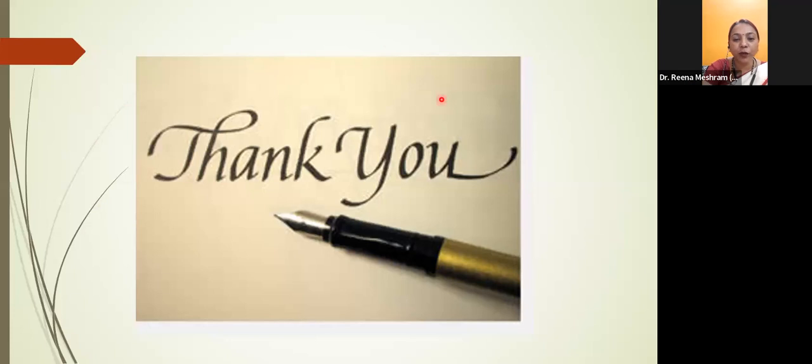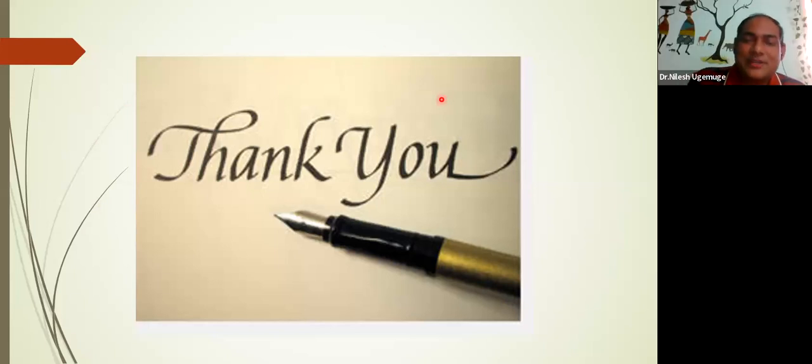Sir, Manjit Singh wants to ask, what is sinter and pre-sinter? Sinter means simply, what we do basically for getting phase purity, whenever we are trying to put material in a furnace. Before that, we heat that material at a very low temperature. Suppose you want to prepare your material at 600 degrees Celsius. Pre-sintering means we heat that material at 400 degrees Celsius for half an hour or 1 hour, and that is what we call pre-sintering. Then at 600 degrees, that is the sintering. Sintering is simply a heating process which we adopt in solid state reaction methods.